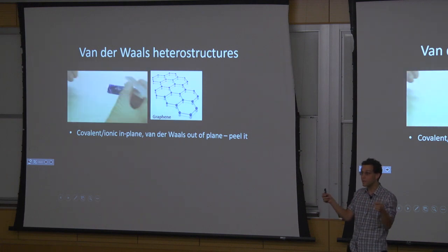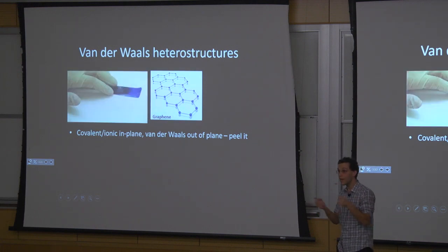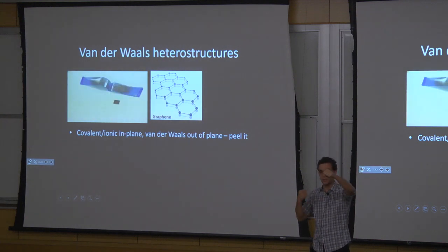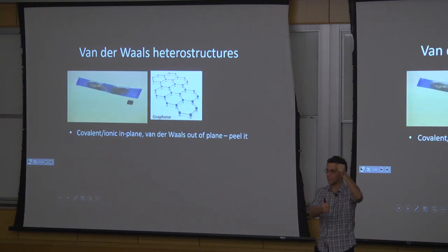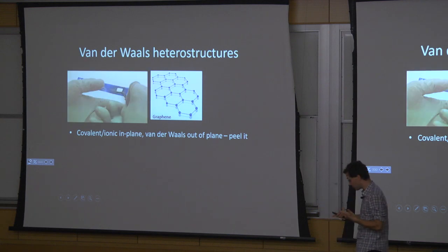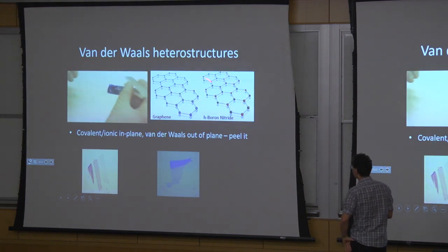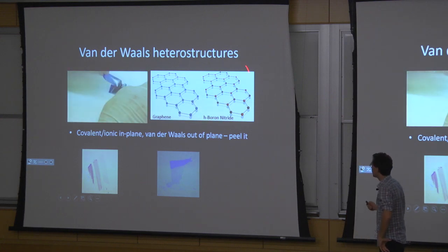And if you're talking about electrons in your 2D material, then what you'd like is for there to be no local charges nearby, because if there's a local charge, it's going to push the electron away, and if it's a positive charge, it'll suck it there. And again, it's going to choose your ground state for you. We don't want that. So the answer to that turned out to be this other material, hexagonal boron nitride.